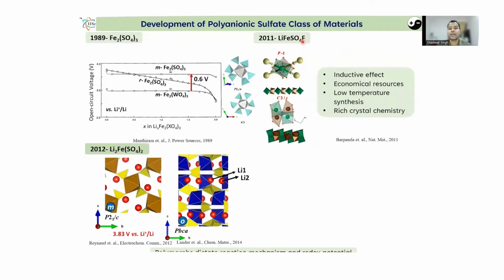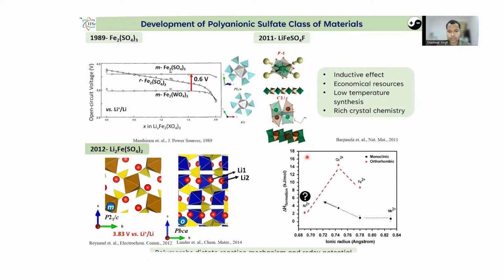However, since these compounds are hazardous because of the presence of fluorine, there is a need to be free of fluorine, and that led to the exploration of lithium metal bisulfate compounds. Now, this family of compounds basically has two polymorphs, monoclinic and orthorhombic, and depending on little structural differences, they will have crystallographically similar lithium, otherwise crystallographically two different lithium sites, and that will lead to different reaction mechanisms as well as little differences in the redox potential.